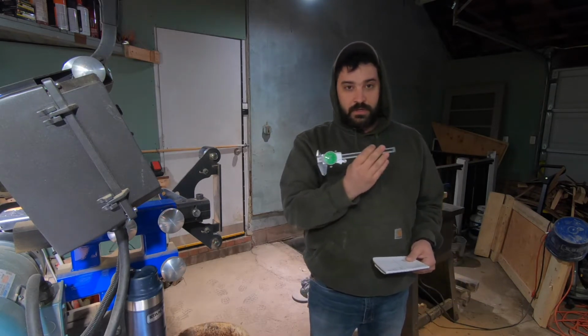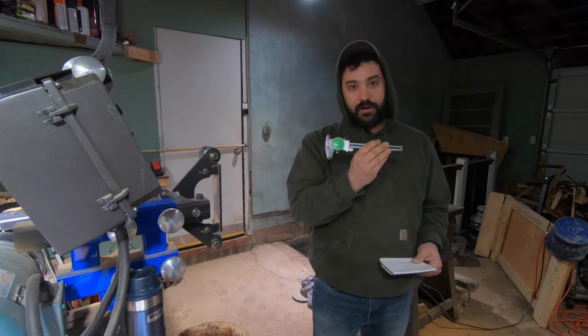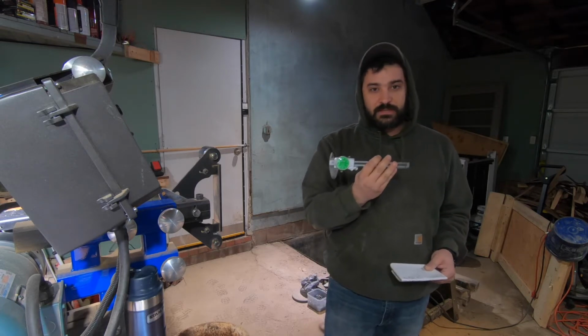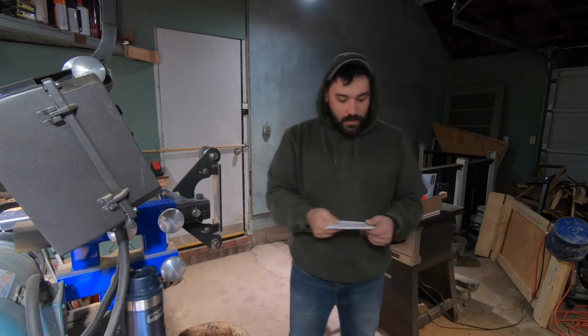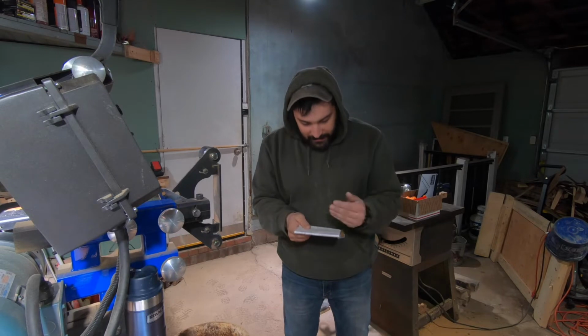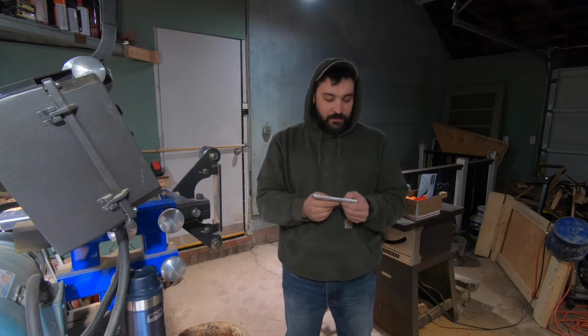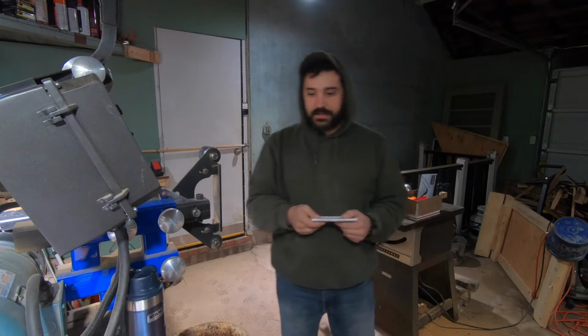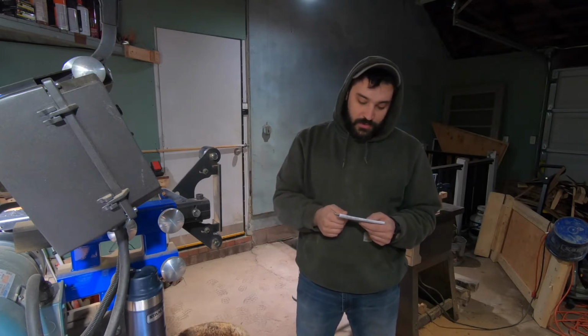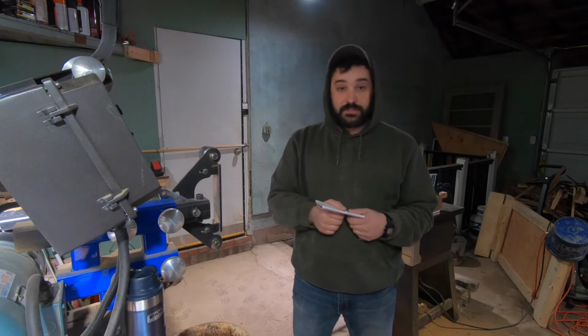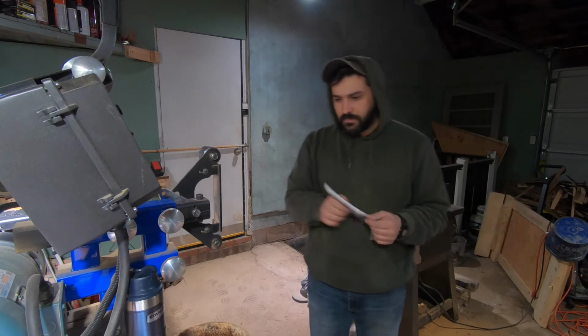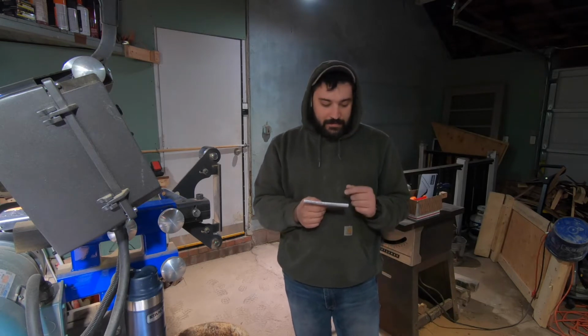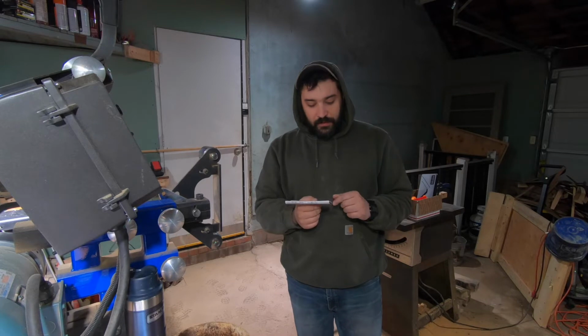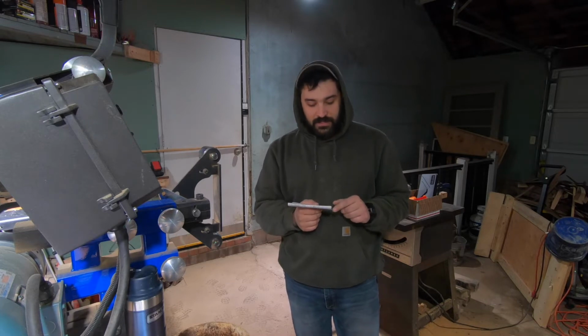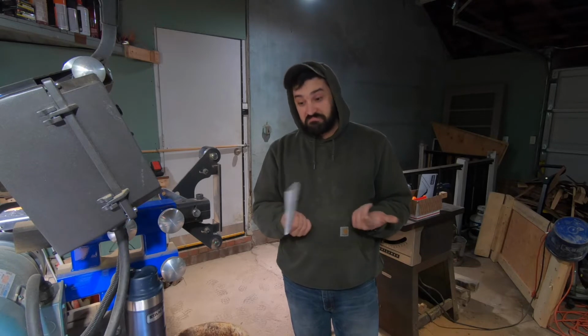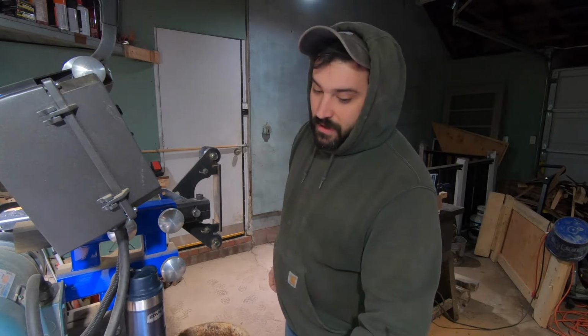And then I also used my new dial calipers. So these are zero error as far as the spec sheet in the box was concerned. I didn't round anything, kind of got it to the nearest decimal. For the behind the edge thickness of the Rat 2 in D2, we have 18 thousandths behind the edge, which is pretty respectable. It is a fairly thin stock. And the AW Bladeworks Proto in D2 has a behind the edge thickness of 12 thou, which is very good for a custom in D2.